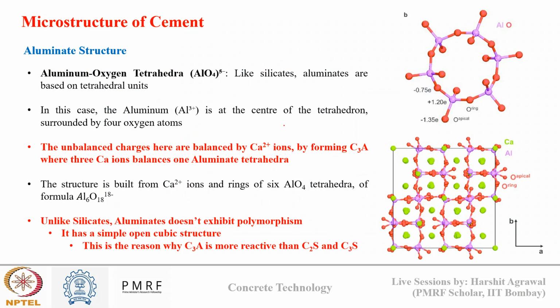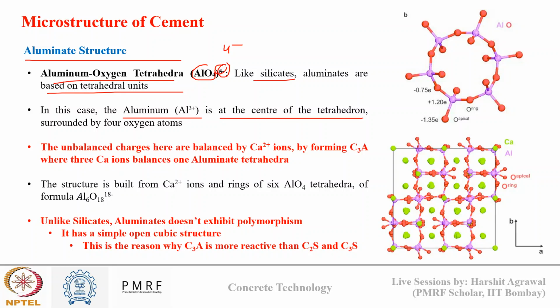Now, that was silicates. If we see aluminates, we have aluminum, aluminum oxygen, AlO4 5 negative. So, like silicates, aluminum also has tetrahedral units. However, in case of aluminates, there are five unbalanced charges, whereas in silicates there are four unbalanced charges. And in aluminate, we again have aluminum at the center of the tetrahedra surrounded by four oxygen atoms, and there are five unbalanced charges present.